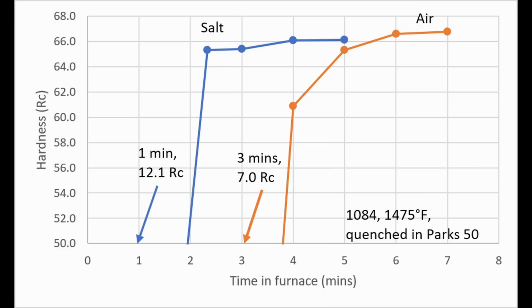After 4 minutes, it was 61 Rockwell, so almost there, but not quite hot enough. At about 5 minutes, we were at about the same temperature as the salt. And then at 6 and 7 minutes, we peaked out at 66 Rockwell, which is about as hard as the steel is going to get.